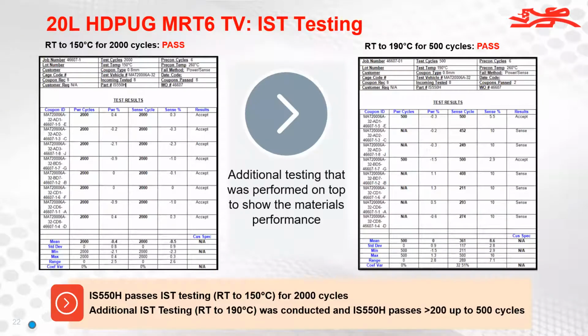Let's turn the knob up to 11 and see what we can do if we cycle from room temperature to 190 C. A lot of customers, OEMs, they want to see this done to 200 cycles without doing the 150 C cycles first. Just do 200 cycles, but we ran this material for 500 additional cycles and it passed that testing. So this is really to demonstrate the thermal cycling capability of the material.